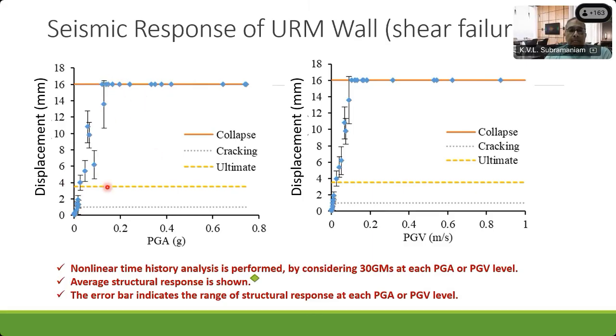the pier, that increases. Now, what is marked on here is the dotted line here represents the cracking limit state. This dashed line here represents the strength limit state, the maximum resistance, and the solid line here is the collapse limit state. And you can see that at a very low value of PGA, most of these walls, which failed in shear under the static loading, were actually cracked. Again, at a very small value of PGA, most of the walls were even pushed beyond the capacity limit. And at a PGA value of around 0.1 or so, you see that most of the walls had also failed.